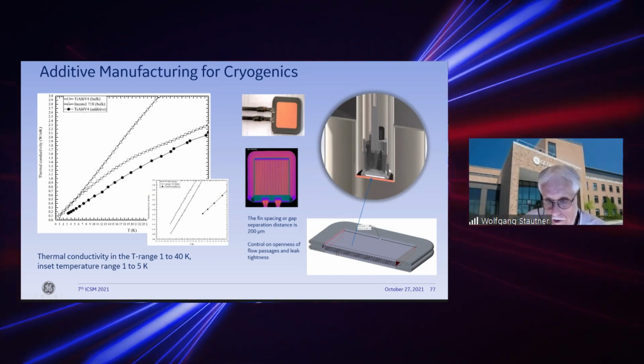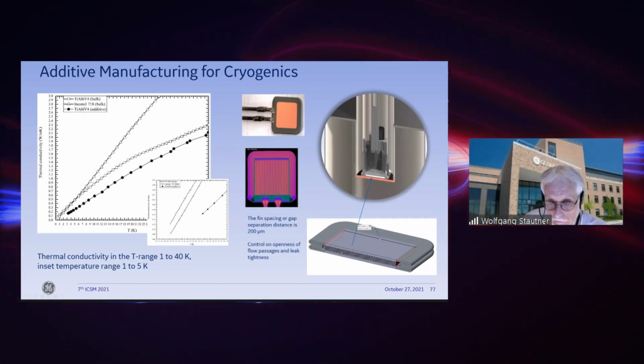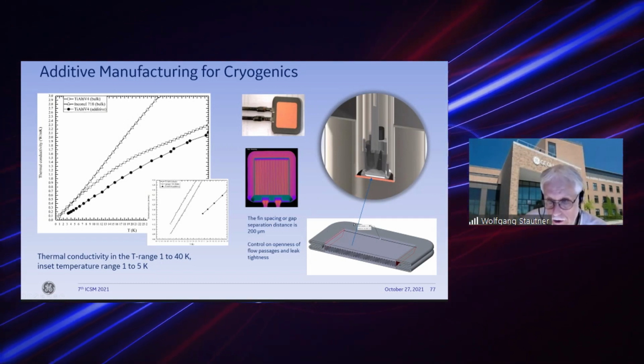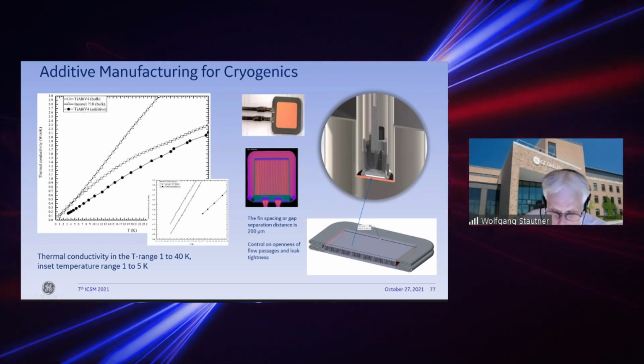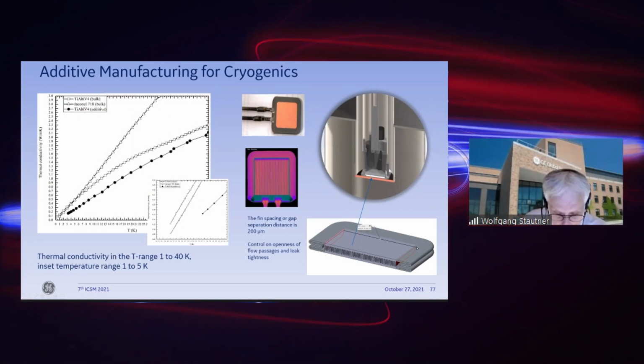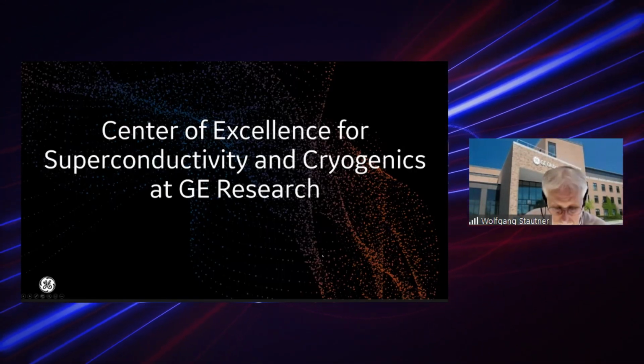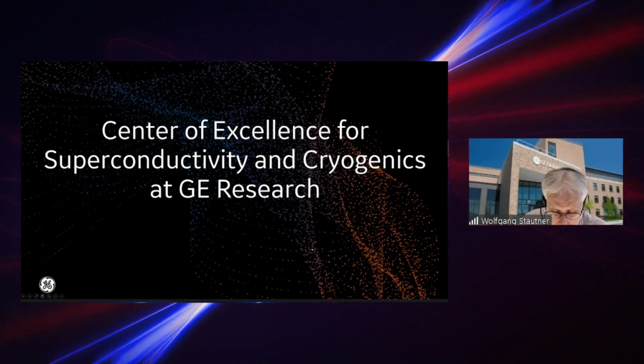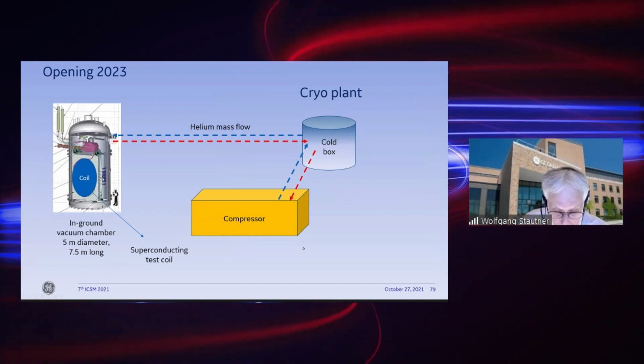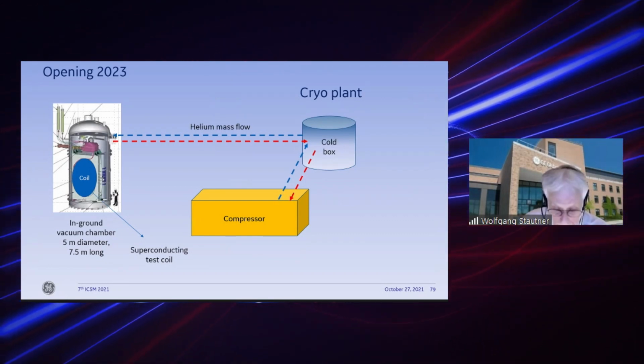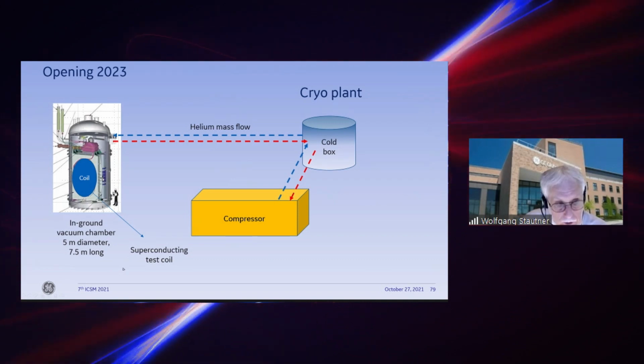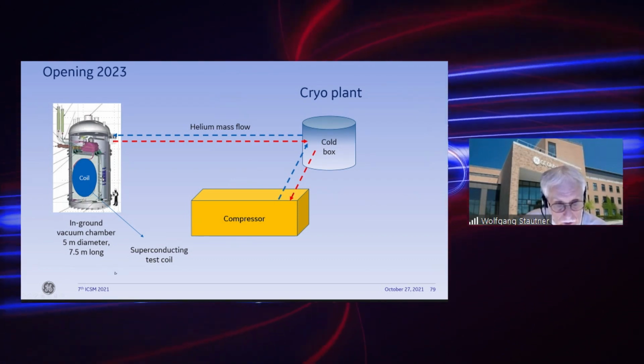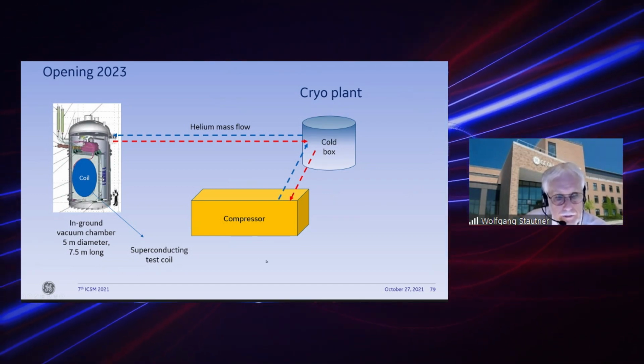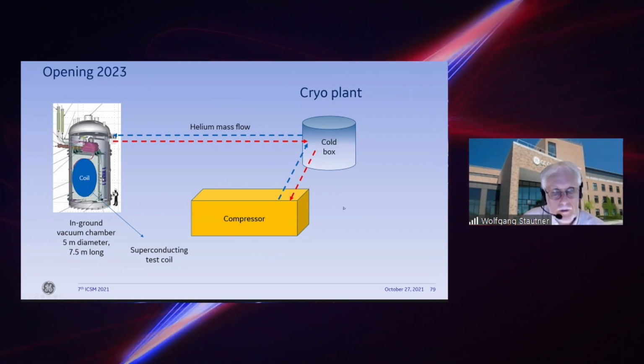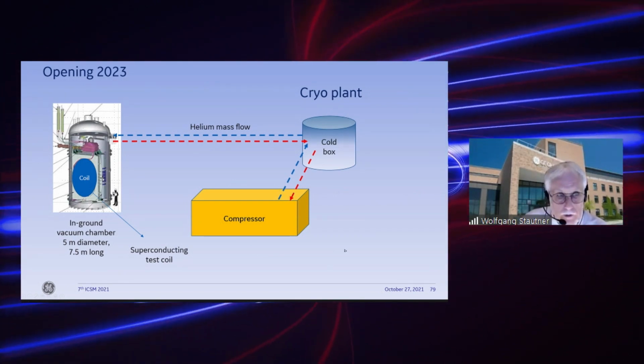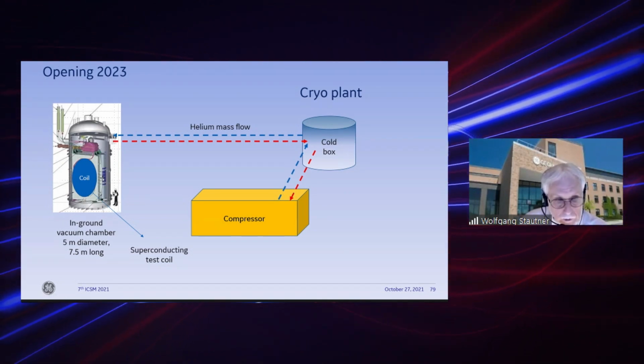And you can see here, this gap is about 200 micrometers only. And it's a very convoluted structure to minimize the thermal conductivity in the axial direction. Now, before we close, let me just point out there's now an opportunity for the research community to test large superconducting coils in our new test facility. It's an in-ground vacuum chamber, 5 meters in diameter and 7.5 meters long, where you are invited to test your superconducting test coils, and it will be opening in 2023. There will be a cryo plant attached to it for easy and fast cool down.